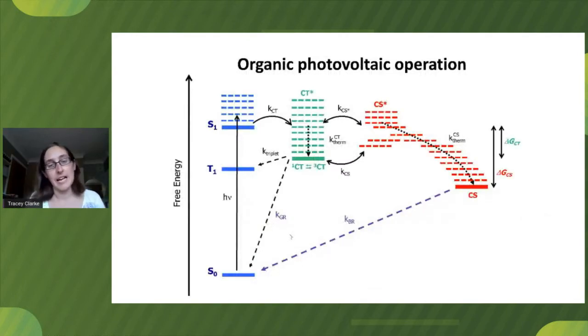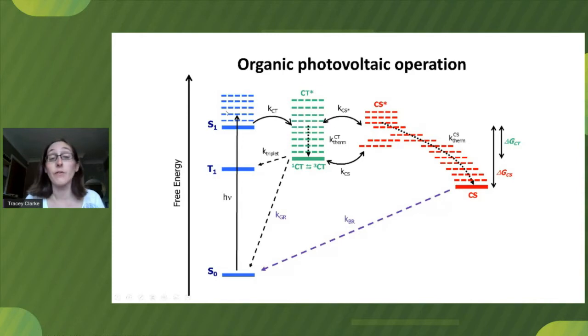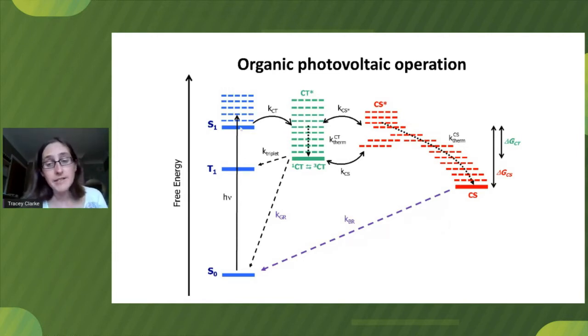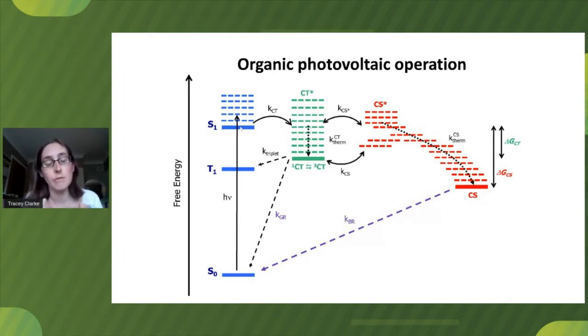This is a very typical view of how an organic solar cell works. We generate a singlet state via absorption of a photon of light by either our donor molecule or our acceptor molecule. This is often called an exciton — a bound electron-hole pair. In the presence of an acceptor, we undergo an electron transfer to that acceptor, but because of the low dielectric constant of organic materials, the electron and hole still remain quite tightly bound.